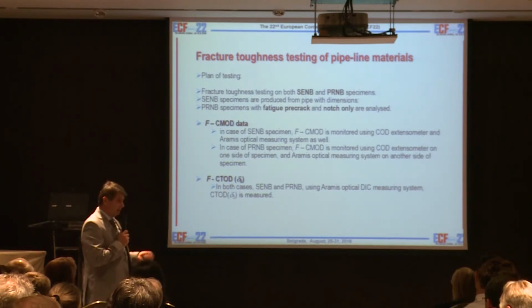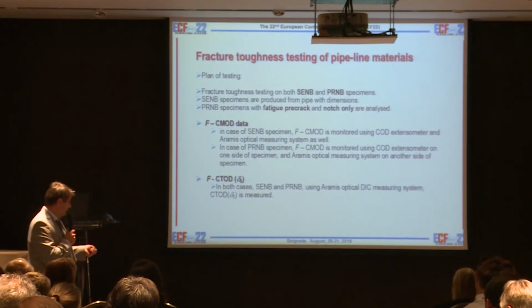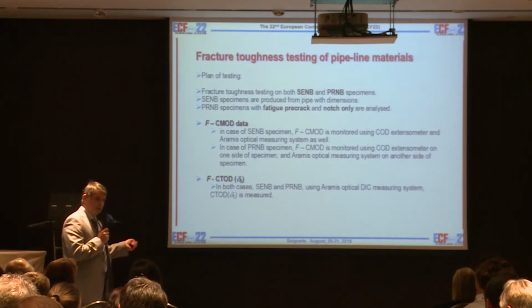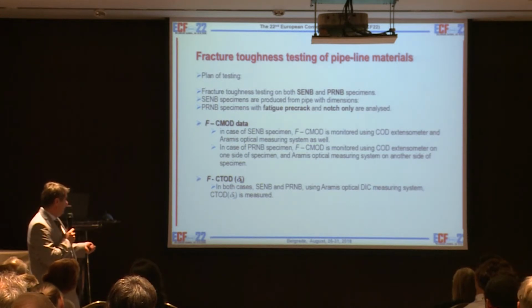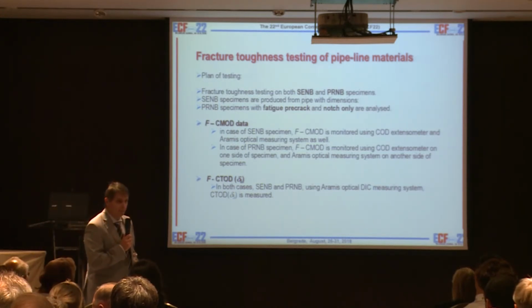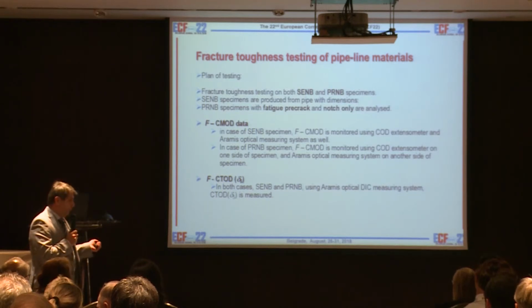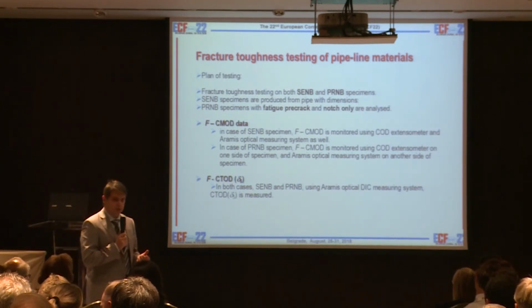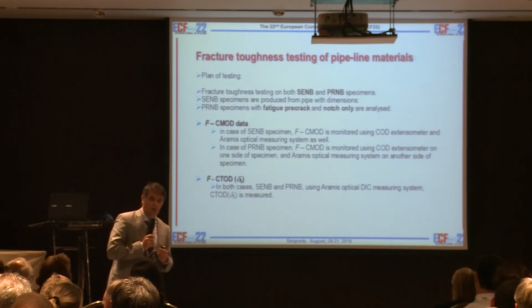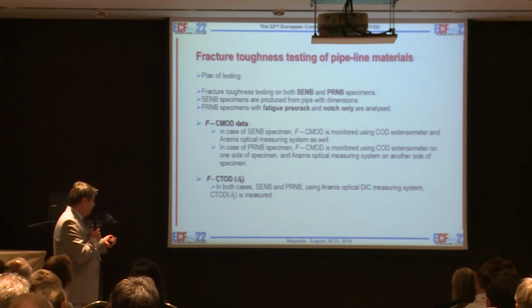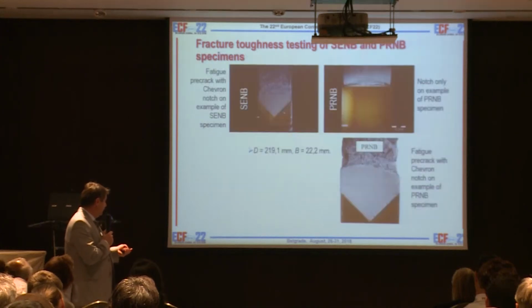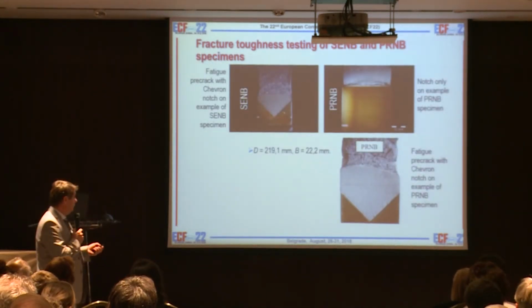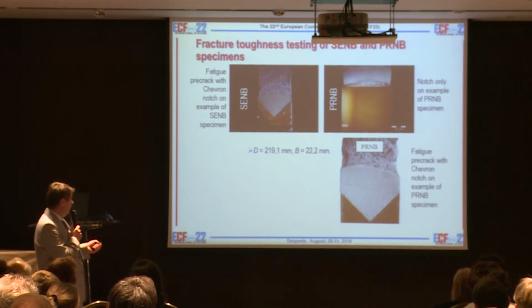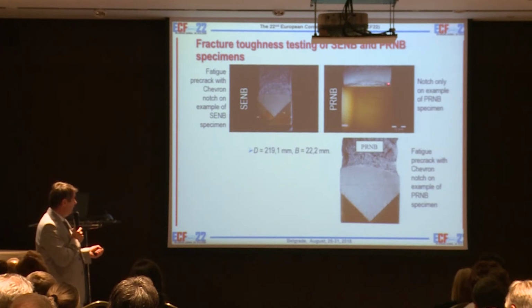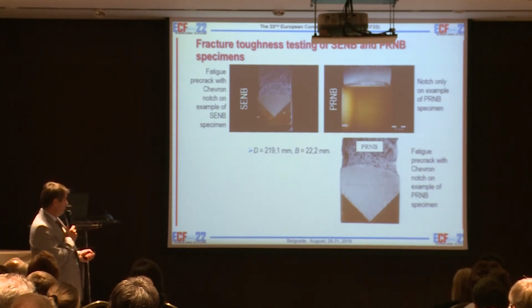By Aramis it is also possible to measure delta 5. This is the influence of my, let's say, director of the Institute GKSS, Professor Karl-Heinz Schwalbe. He developed delta 5 to measure toughness, because in this case you don't need a shape function. So you can measure toughness directly without knowing the shape. And we measure this also using the delta 5 technique. If you use the notched pipe ring specimen, then during loading the first step is like that, then you have the blunting, and then the start of crack propagation.